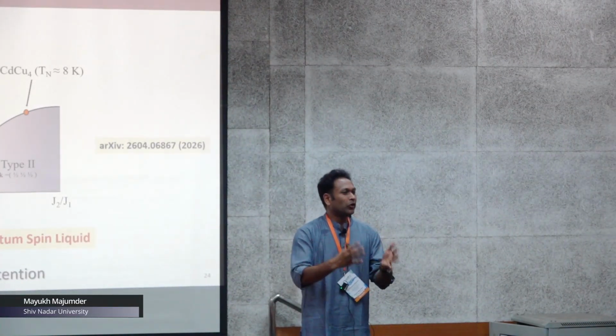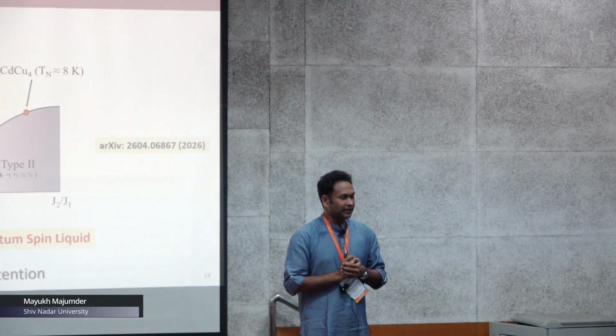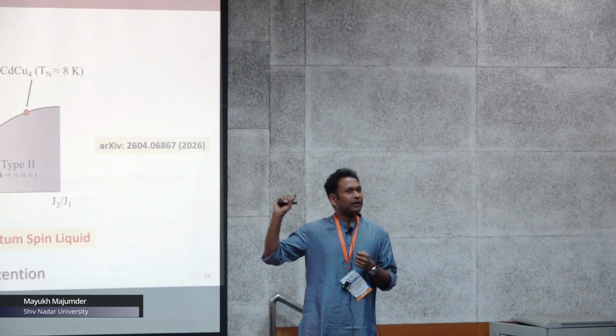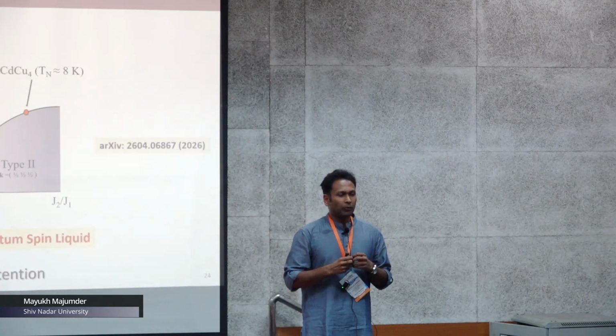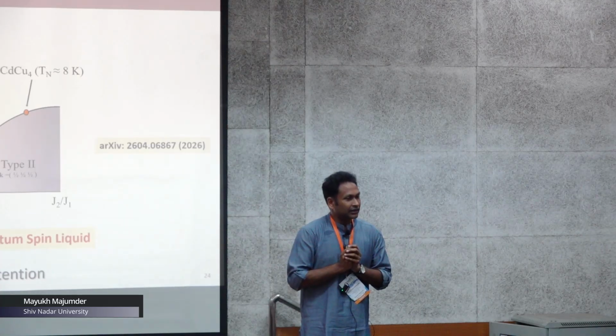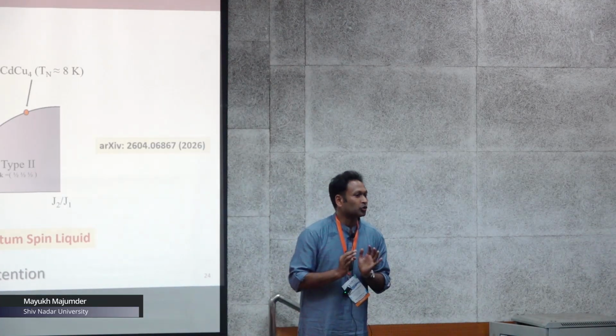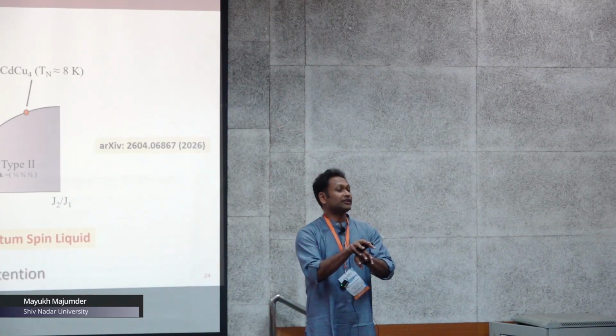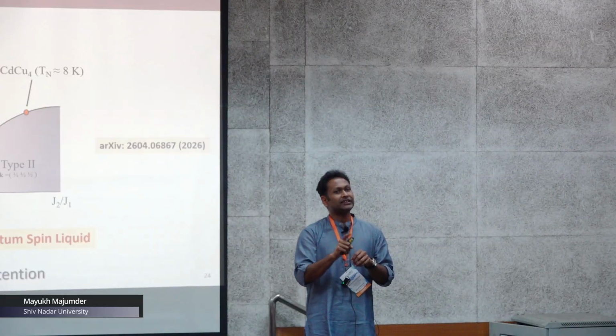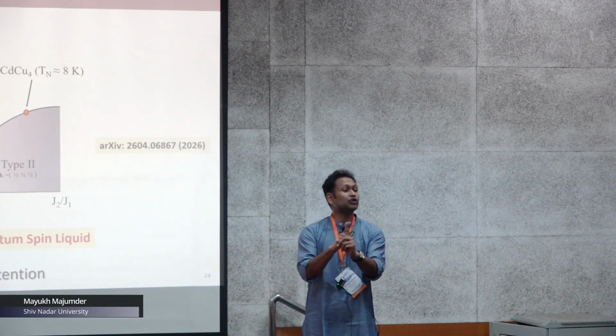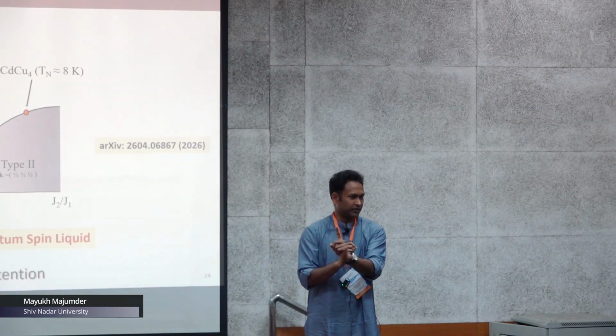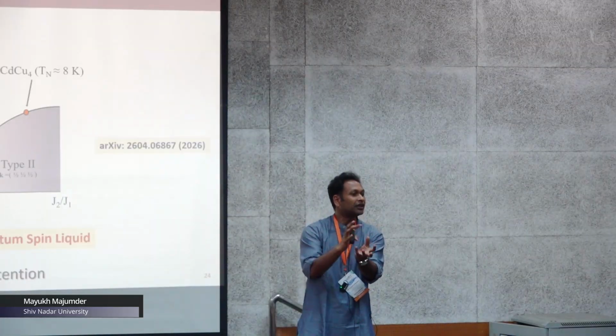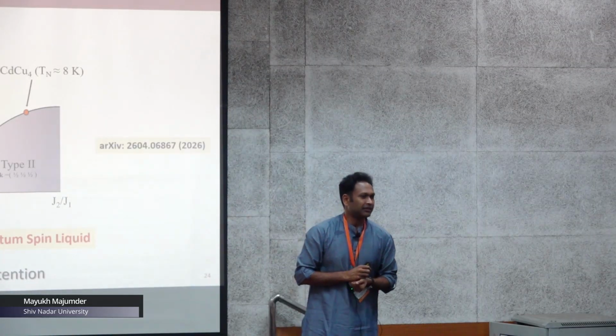Of course, that may also give rise to a spin glass type of thing, but for this compound, people have performed different experiments, completely discarding the possibility that there is spin glass as such. But there is a phase coexistence. The phase coexistence is only happening because of its close proximity to a quantum spin liquid, not due to disorder-induced phase separation. Yeah, that is our feeling.